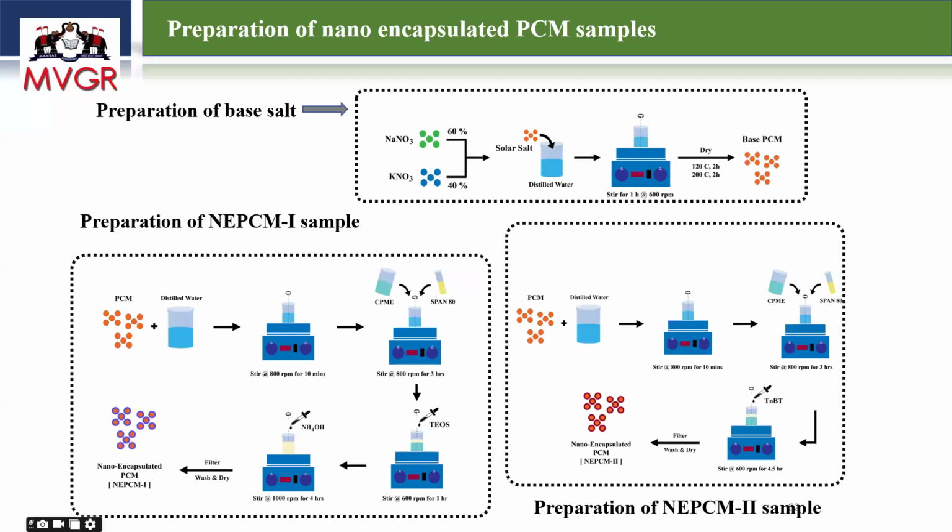First, we take this salt and mix it into water, and once the solution is completely made, we can make that eutectic PCM material. A eutectic is a combination of any two materials. Here I'm using two salt materials; I'm developing an inorganic eutectic mixture.